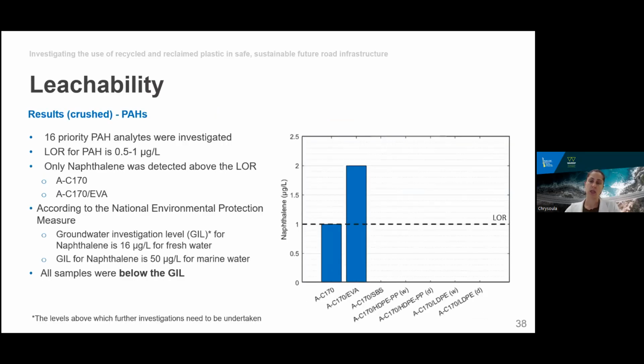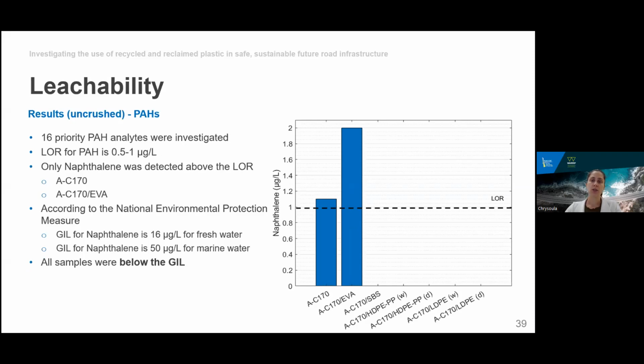Before I present the results here, I do need to say that I will talk a lot about groundwater investigation level, abbreviated here as GIL in this presentation. According to the National Environmental Protection Measure, this is the level above which further investigations are required before they are deemed safe for the environment. Now, looking at the results for PAH leachates from a crushed loose asphalt mix, only those of C170 and EVA modified C170 were above the limit of reporting, and all were below the groundwater investigation level. The results from the uncrushed loose asphalt mix were the same as those of the crushed sample as far as the PAHs were concerned.